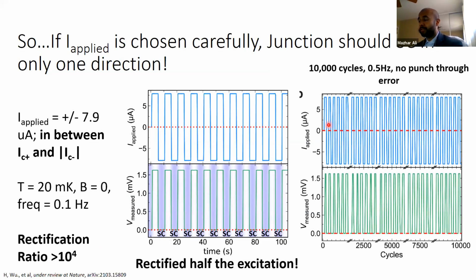But the other fun thing we just decided to check, just to be sure, is, we sped it up a little bit because we didn't want to run this for a lifetime, and ran 10,000 cycles and just watched it. Did we have so-called punch-through error, where when we flip the sign, again applying the same magnitude, in this case positive current, do we accidentally end up in a superconducting regime again? As in, do we punch through that delta IC because of instability, because it's wiggling around, because of Joule heating or whatever? And the nice thing is, no, we don't.